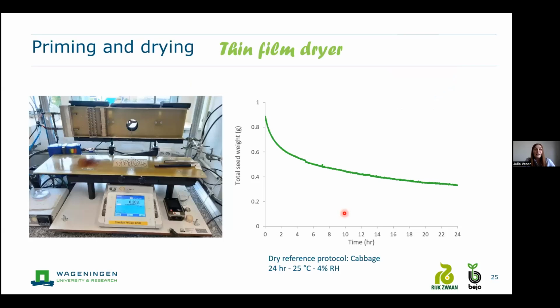For the drying, we use this thin film dryer. It is originally used for polymer films that are dried on this little plate and observed during the drying. But for us, it works very well. We can add our seeds on this little plate, and this plate is connected to a scale so that we obtain this really nice drying curve over time of our seeds. In principle, this lid is closed, and we have a nice airflow distribution over the seeds, so the seeds can dry in a hot air stream.